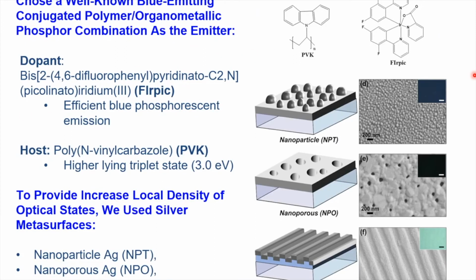For this study, we chose a very well-known blue-emitting organometallic phosphor, FIrpic, as well as a conjugated polymer host that's used to deliver the charge to the emitting phosphor. And we chose three different metasurface morphologies: the nanoparticle case, the nanoporous metasurface, and the one-dimensional silver grating with two different periods.